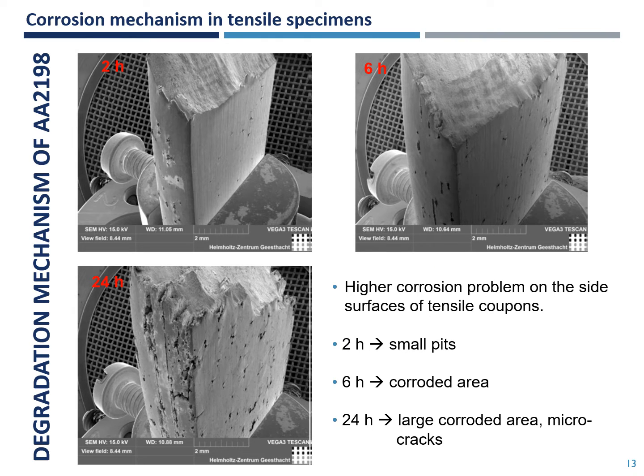Investigation of the corrosion mechanism on tensile specimens of aluminum alloy 2198 through SEM analysis showed that the corrosion problem is higher on the side surface of the tensile coupons. Small pits are evident on the corroded surfaces of the specimens exposed to EXCO solution for 2 hours, while a higher corroded area with more pits is evident after 6 hours. However, after 24 hours of corrosion exposure time, a larger corroded area with several microcracks is evident.